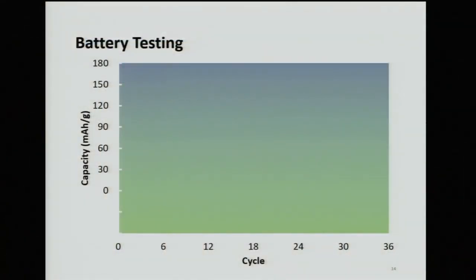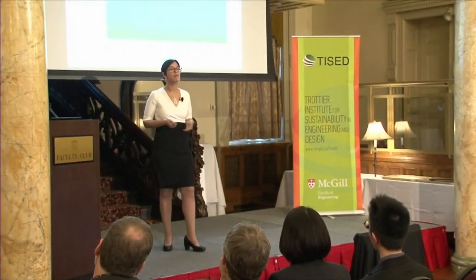But for lithium titanate, that is what we used, the theoretical capacity is 175 milliamp hour per gram. Now, this is actually quite low, but we have an advantage with lithium titanate, and it's that we can deliver that power, that capacity very fast. We can also charge it really fast, and you want to be able to charge your phones fast, but you want to be able to deliver power fast when you're using something like a power tool that needs fast power delivery.